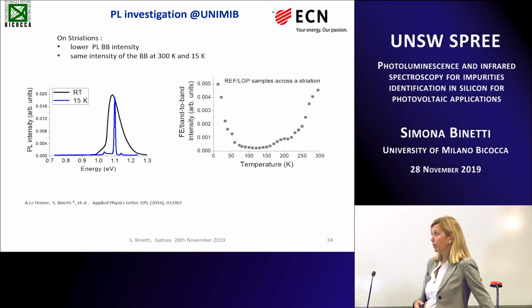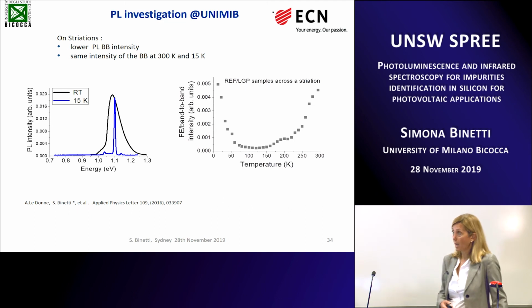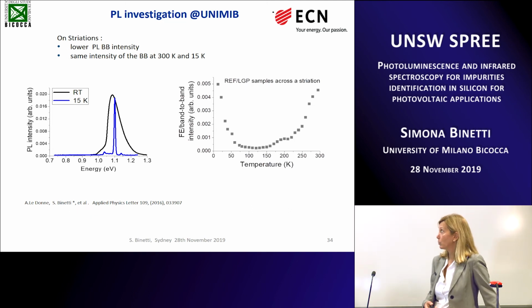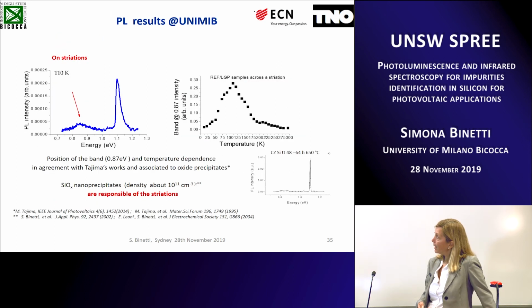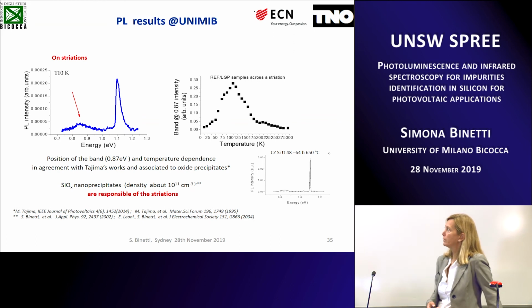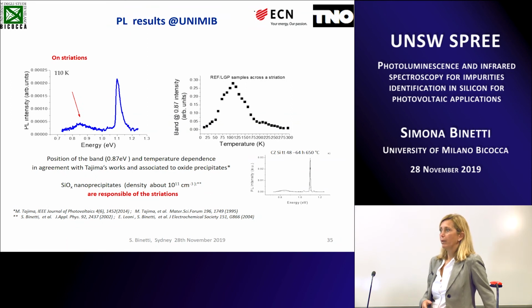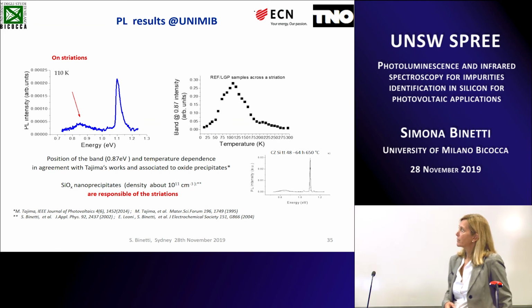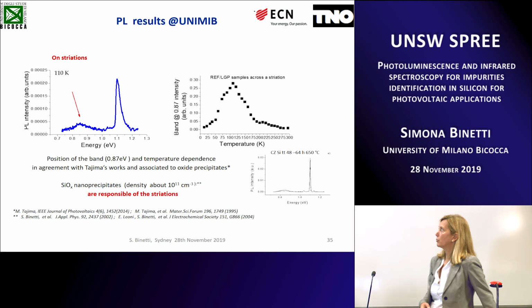Normally at low temperature you have a very high intensity of the free excitons, much higher than of the band-to-band transition. And we have seen also there was a strange behavior of the intensity of this band versus temperature, but we have seen that at the same time there was, on striations, a broad band around 0.87 that has the opposite behavior of the band-to-band peak versus temperature. And this band was exactly the same that we have detected in Czochralski silicon sample heat treated at 650 degrees C, so it is related to oxygen precipitates.